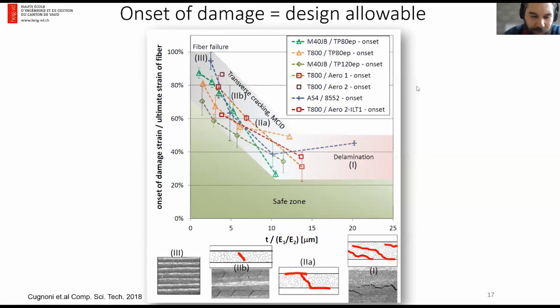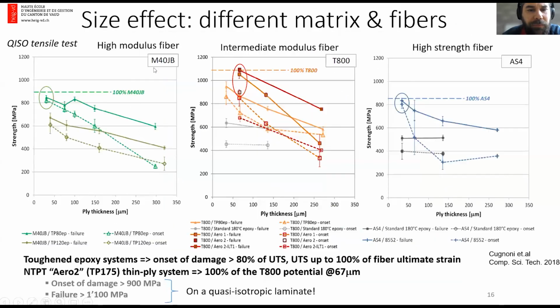Maybe there's something I can show. You see this gray curve here. This is a carbon epoxy system where the epoxy matrix was not toughened, a raw matrix without any toughener inside. This high temperature epoxy is very brittle. It doesn't have good fiber matrix adhesion or good ductility. And you can see that in this case, there's no ply thickness effect.